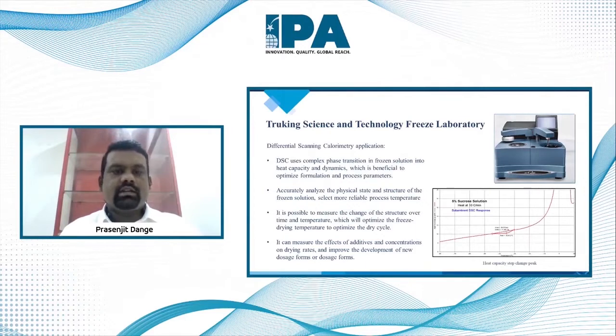Another instrument is the DSC, which we also call differential scanning calorimetry, which determines the glass transition temperatures. DSC is an instrument designed to detect the changes in the specific heat of materials as it takes place while passing the glass transition. Many lyophilized products stay in an amorphous form after drying. As water shows a softening effect, the glass transition temperature of the amorphous phase is directly related to the entrapped residual water content. Thus, DSC can furthermore be utilized for determining the drying status of the materials as well. So not only finding the glass transition temperature, but we also use this for finding the drying of the product.